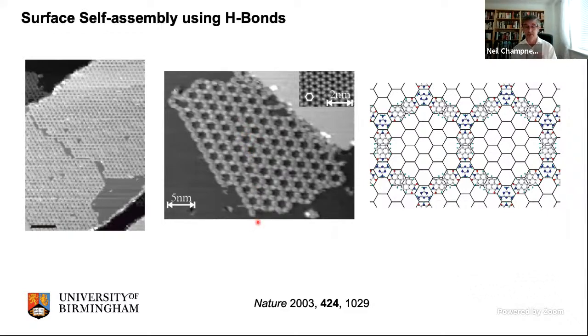The thing which is amazing about this, to me as a chemist, is you can see everything which goes wrong during the self-assembly process. So, for example, there is a missing molecule here. There should be a molecule there, and it's not there, right? There should be a molecule here, and it's not there. And you can see all these defects because you're actually working at the molecular level. And this is completely different to almost any other technique that chemists use. So crystal diffraction is an averaging technique. NMR, you're looking at billions and billions of molecules at a time. Here, you're looking at individual molecules, and you see everything which goes wrong. So in some sense, this is a porous framework, right?